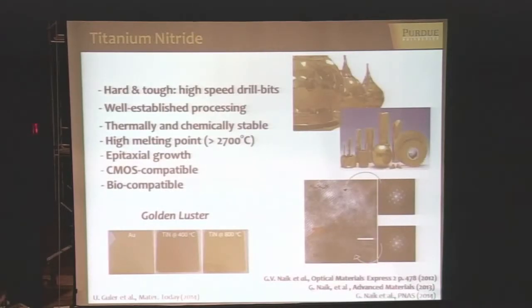So let me start with these new materials, and the one we've studied most so far is titanium nitride. It's a very well-known material used for many other applications. Ironically, it's used in electronics and chips to prevent diffusion of copper, which is also a common plasmonic material. But it was never really explored as a plasmonic material itself. As you'll see, it's actually a very good plasmonic material, in many regards better than gold, for example. What we know about this material is it's hard and tough.